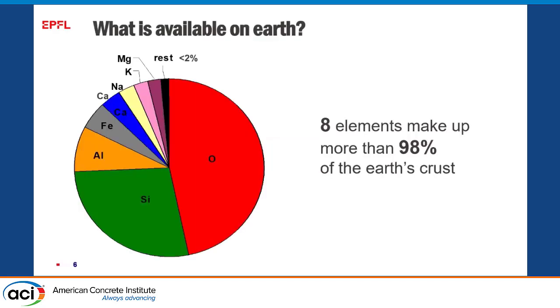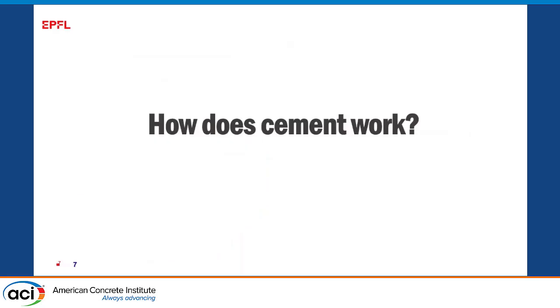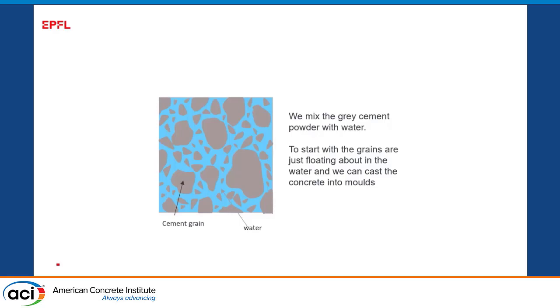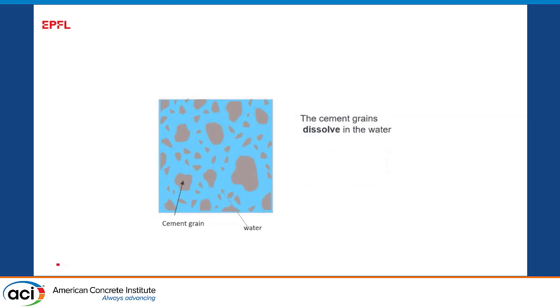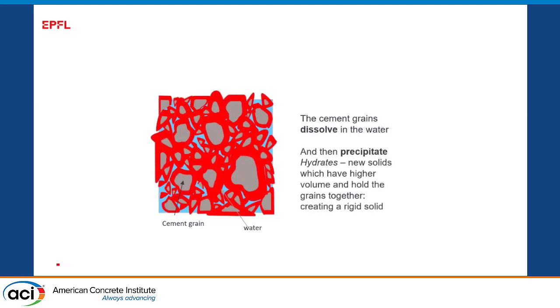And it basically comes down to the composition of the earth, that just 8 elements make up more than 98%. And then if we look at how these 8 elements work in the context of cement, well, you know, 101, how does cement work? Basically, you have this gray powder floating around in water. And first of all, the grains dissolve like sugar dissolves in your coffee, and then they precipitate these new hydrates. So you need to have a chemistry where you can have this dissolution and this precipitation.